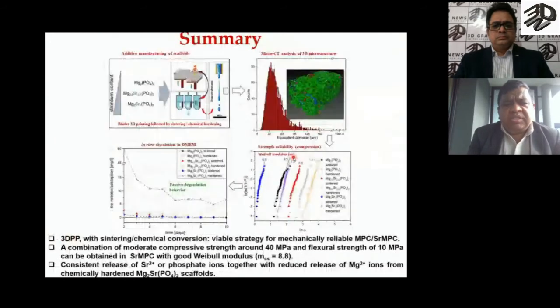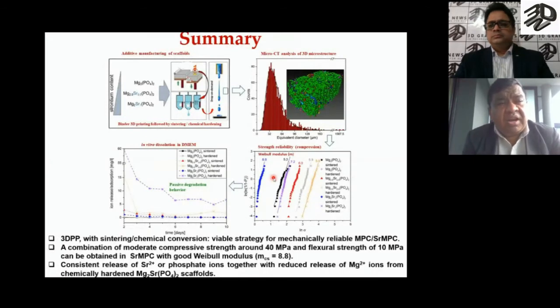So we have done other techniques, for example dissolution behavior, because dissolution is very important, and it shows a passive degradation behavior of magnesium phosphate cement. Now, many clinicians are a little bit hesitant to use ceramics because they do not have much strength reliability, like it can break at any point of time. That is the general concern.